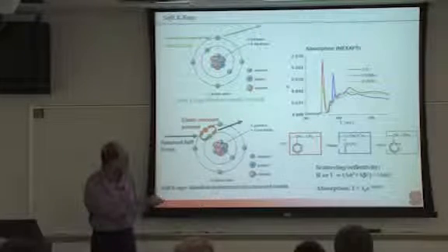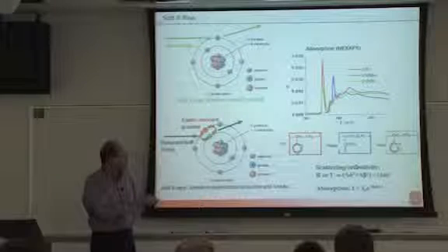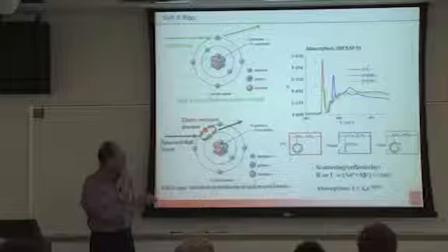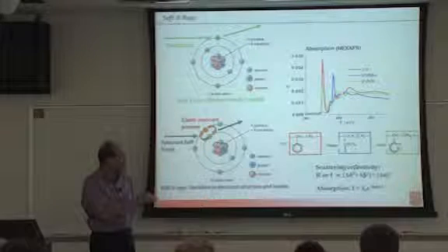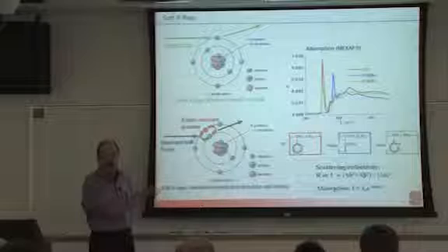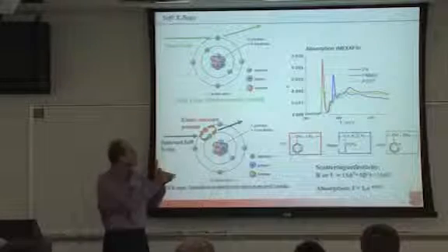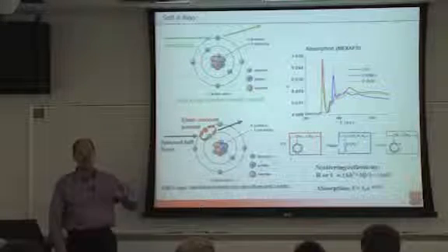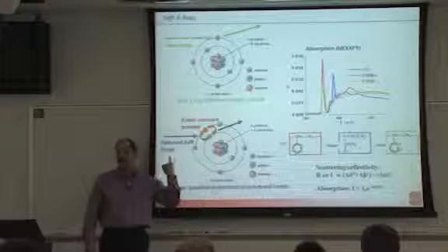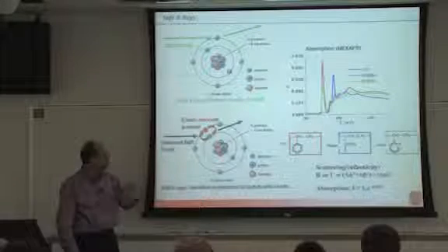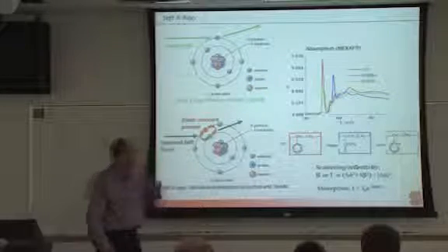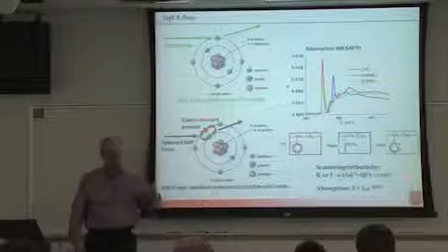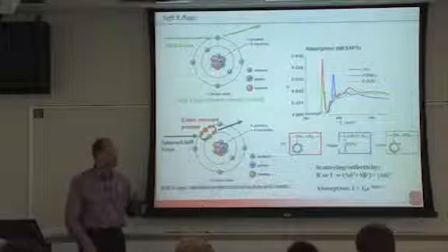Okay, so here are some prototypical, classic amorphous polymers, not semiconductor polymers, but just to enunciate the principle. So I have polystyrene, unsaturation here, I get the sharp resonance, and this is now in absorption, that has to do with the promotion of an X-ray from a 1s electron into the unoccupied pi star manifold. And with it, there's a dipole transition moment. We have polarized X-rays, and that will later allow us to be sensitive also to orientation of bonds.